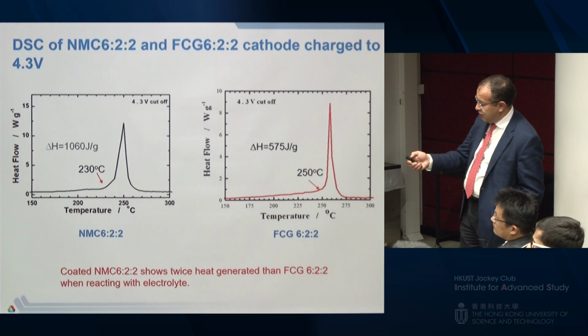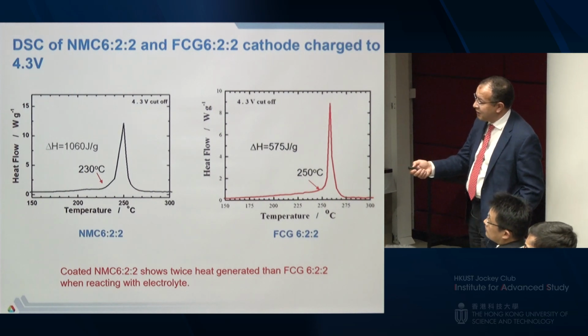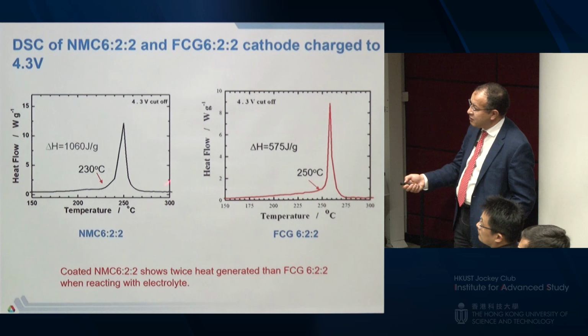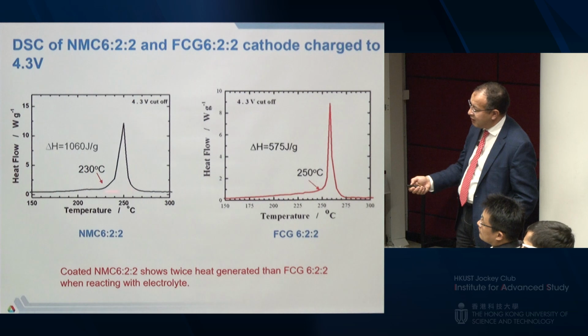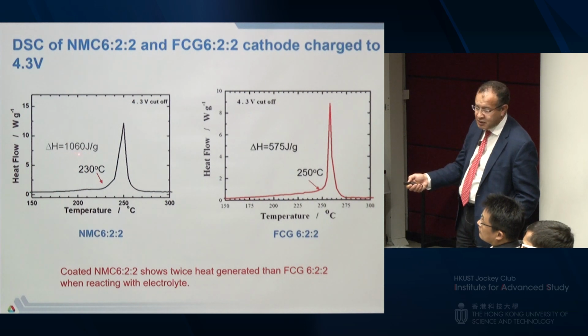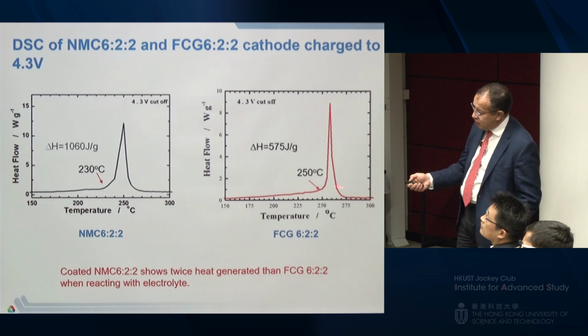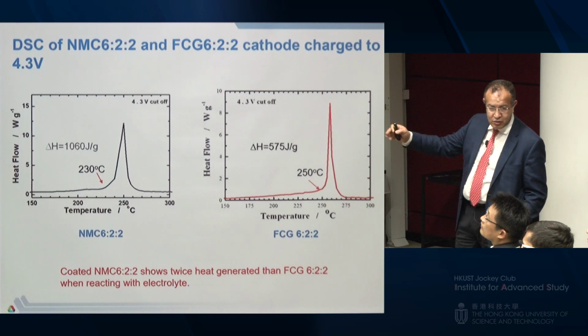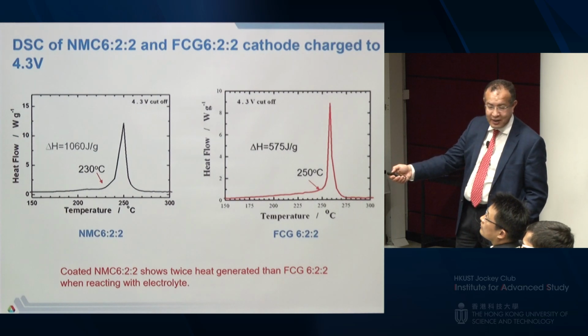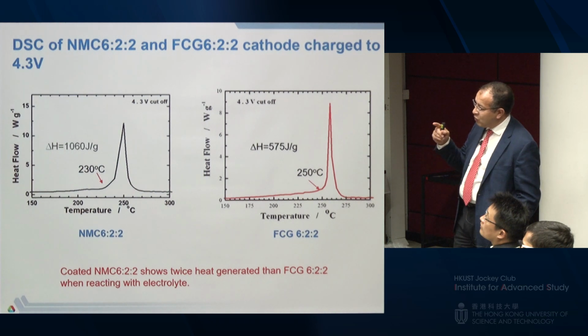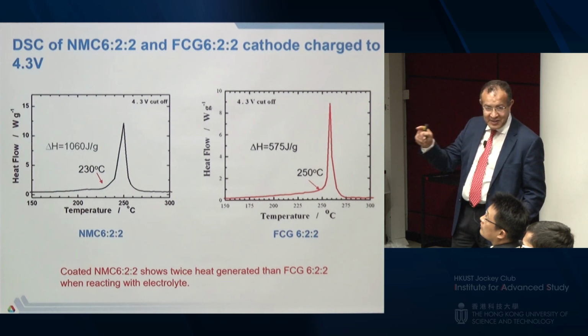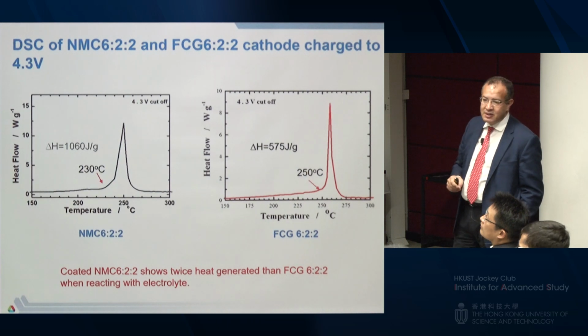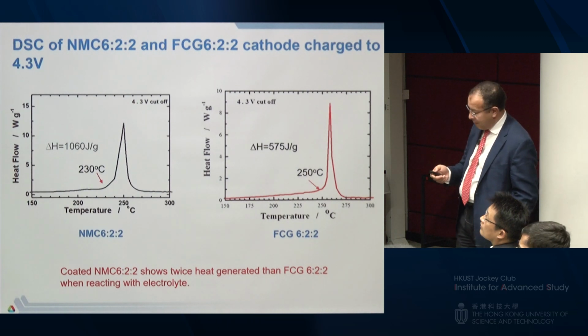So this is a DSC of these two materials, so we compare apple to apple. You can see clearly that in the case of NMC, when you fully charge it to 4.3 volt and then react it with the electrolyte, the enthalpy of reaction is higher, about 1,000. And the onset temperature is also higher, better than the NCA, but it's lower than in this case here, where you have half the energy and higher onset temperature. So the safety of this material is much better as well. So we hit two birds with one stone. We improved the cycle life, we increased the energy, and then we increased the safety. I should say three birds, I would say.